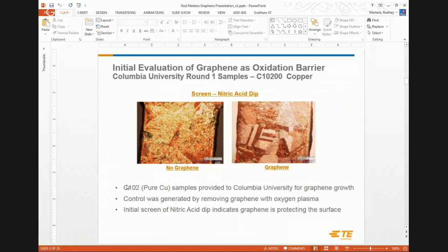We took that strip, and this was basically our look-see to see if it's going to work. And then we etched it with oxygen plasma to remove the graphene on one piece, left the graphene in place on another, and then did a nitric acid dip, which is basically going to really go after the copper. And you can see on the left with no graphene, we had significant corrosive attack of the copper. Whereas on the graphene, if anything, we may have decorated the grains a little bit, but it's very clear and very clean. So clearly the graphene is demonstrating some resistance to corrosive attack.